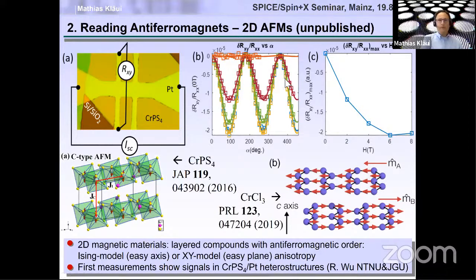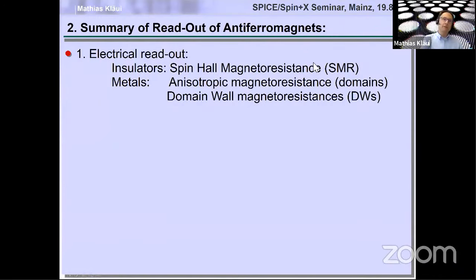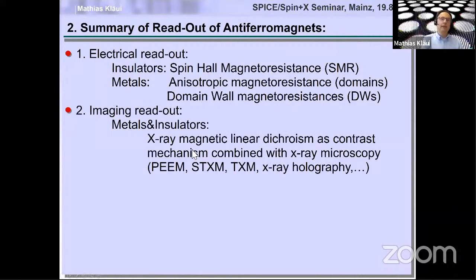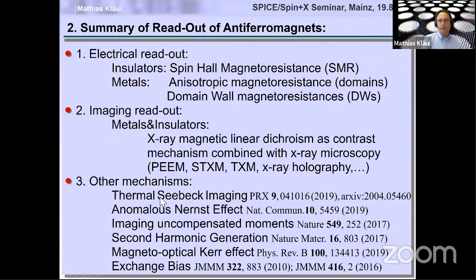So to sum this up, the electrical readout is possible in insulators using spin-Hall magnetoresistance, and in metals using anisotropic magnetoresistance and domain wall magnetoresistance. And for imaging, we can get readout by X-ray magnetic linear dichroism as a contrast mechanism. But there are also other mechanisms that I didn't introduce today, but that are quite important, such as thermal spin-Seebeck imaging, anomalous Nernst effect, imaging uncompensated moment, second harmonic generation, magneto-optical Kerr effect, exchange bias, and so on. So there are a lot of ways to read out antiferromagnets, but it's important that we can do that electrically.